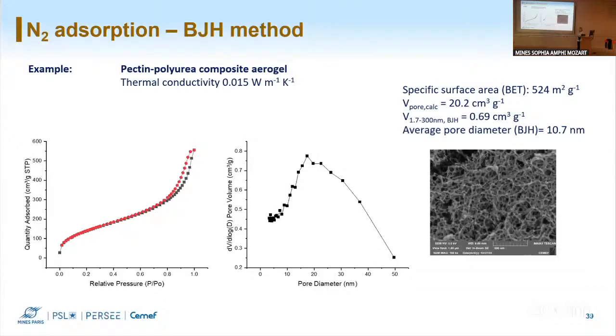So for this reason, we say that we cannot consider the method valid for pore size distribution. We measure surface area, but we chose not to present it as a measure of pore size distribution. And did you consider mercury porosimetry? Does it crush the material? We have not tried. Conventional mercury porosimetry should not work because you crush the material. We have very small pore sizes, but I know it's still possible to make some evaluation. If you know these struts, that's feasible even with crushing, but not with Washburn's law. Maybe it could be considered as an alternative. Yes. We could also consider thermoporosimetry, but we don't have any of this equipment, so we could not evaluate.